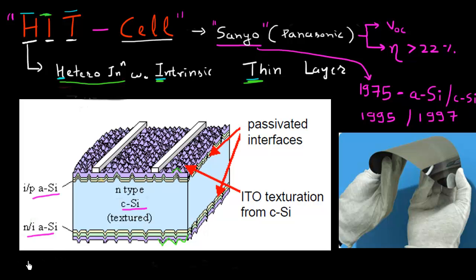One thing I already mentioned was that this cell can be processed at a low temperature. The whole processing can be completed at very low temperature as compared to conventional cells which require temperatures of more than 800 degrees centigrade. As a result, there's very less damage caused in the crystalline silicon. Usually if you subject your low grade silicon to high temperature processes, there's defect formation and cluster formation inside the cell. But since the processing is completed at very low temperature, it benefits from the absence of these high temperature processes which cause defects.